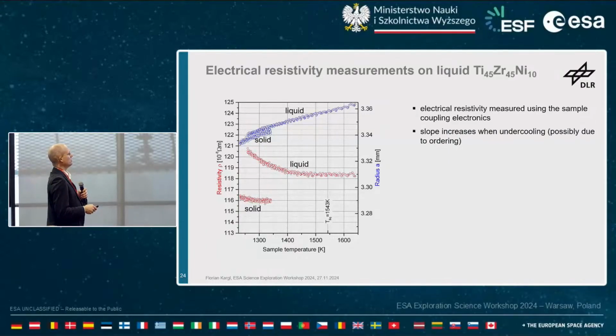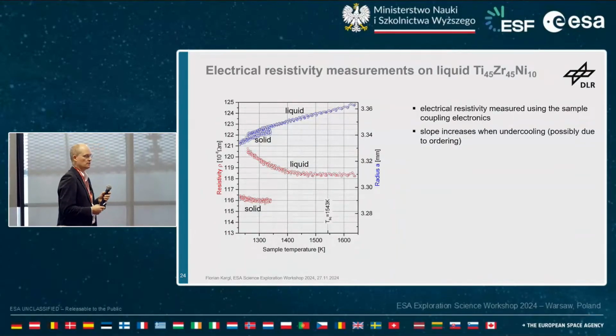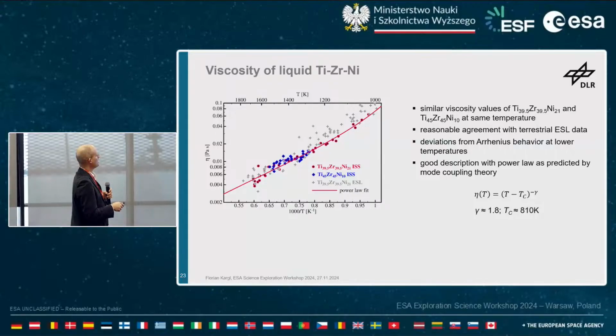The link now to the structure, and so there must be an origin perhaps also in the structure, is the measurement of the electrical resistivity. So please focus on the red curve here. So this is electrical resistivity as a function of sample temperature. So again, here's the liquidus, we undercool the sample. And what you see here is that this resistivity is rising here. It's more or less constant initially, and then it rises. And resistivity is relatively sensitive to structural changes on a shorter scale. And so this could be an indication that there is, let's say, some ordering going on in the system at these low temperatures. If you look here, 1400 degrees, in this area, it's roughly where this lift of viscosity happens. So this seems to align somehow.